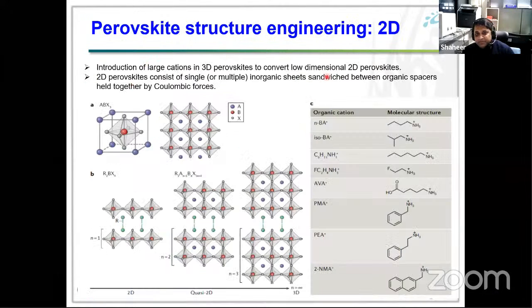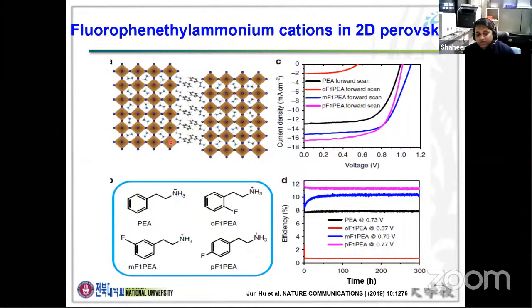So like this one. As we know, the typical ABX3 type perovskite shows a 3D structure. If we introduce a long chain spacer in between the 3D structure, it changes the 3D structure to a 2D structure like this. The good thing about introducing this kind of spacer is that it increases the performance as well as the stability of the device.